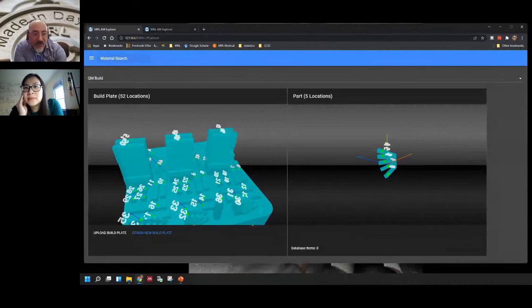So this is where it comes to the paper I shared with you with the crystal tracking. We developed the methodology independent of the FEM mesh at all. SimuFact implemented that very well. They use what other tools use, particle tracking, and in the particle tracking, you have a marker within the FEM that's able to average the information about it and export it. And once it's exported, now you have a material model that you don't need to make a mesh. What you have is a database of the thermal profile as a function of the location, and then you are calling it with the crystal tracking. And the crystal tracking is a volumetric information between 4 corners. And we demonstrated that using the deformation gradient for large plastic deformation in the paper that was published in 2017.